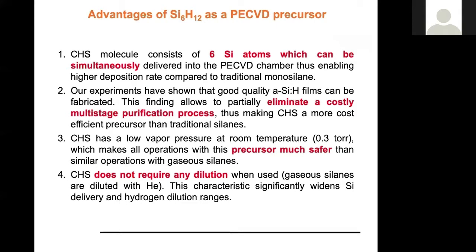Other reasons I've alluded to before: the weaker silicon-silicon and silicon-hydrogen bonds. In the past, we've demonstrated that high quality amorphous silicon with hydrogen termination films can be fabricated, and this can be done in a single step, eliminating a lot of the costs associated with making such materials. And because CHS has a low vapor pressure at room temperature, it's safer to handle than gaseous silanes.